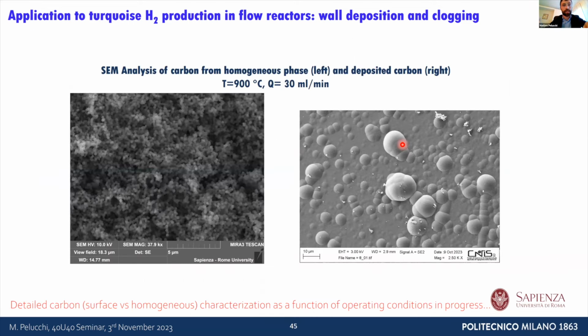We're also trying to characterize the carbon that we're forming. In this case, you see some SEM images: on the left side, the homogeneous phase formed carbon, and on the right side, the deposited carbon on the surface of the reactor.